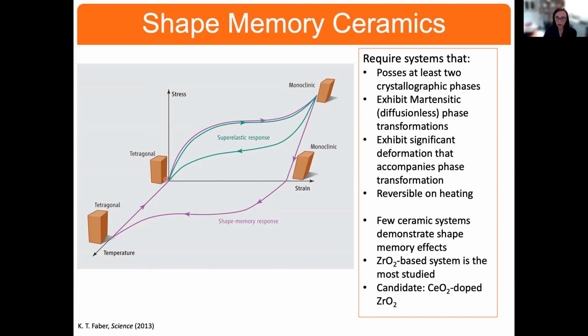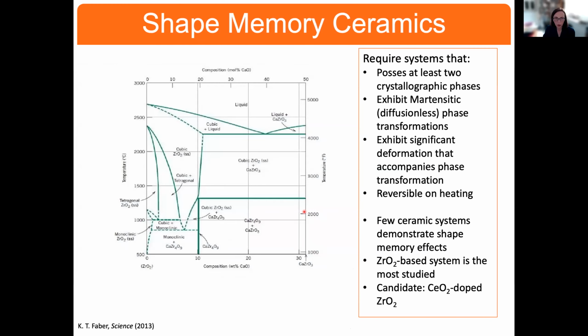So in both these cases, whether they're super elastic or shape memory, this undergoes this crystallographic transformation, with large volume changes that accompany this. And there are a few ceramics that demonstrate it, in particular zirconia-based materials. And you can see this on this phase diagram of zirconia, and this is calcia. But in this region, you see these various phases: tetragonal phase, monoclinic phase, over these temperature ranges. But it's important to know that these exhibit these martensitic transformations.